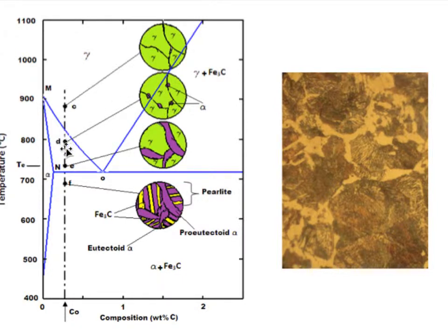And when the temperature goes down, the phases along the grain boundaries are going to grow and be thicker and thicker. If you compare to the picture to the right, which is a real micrograph of a structure of this type of alloy, we will see that these white areas are the ferrite phase, and we can see rather clearly that it's lying in the original austenite grain boundaries, round like this, as we see in this picture.